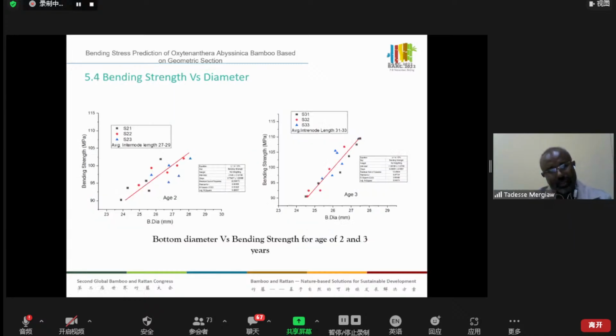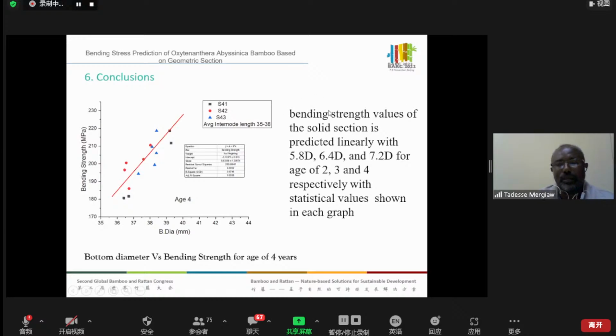And the other result from this research is the bending strengths. So the bending strengths versus the diameter ratio, and bending strengths versus bottom diameter. Three types of specimens were conducted, and here is shown the result, similarly at age 3 and at age 4. So the final bending result values, the solid section is predicted linearly with 5.8D, 6.4D, and 7.2 times D for age 2, 3 and 4 respectively, with the statistical values in each section.